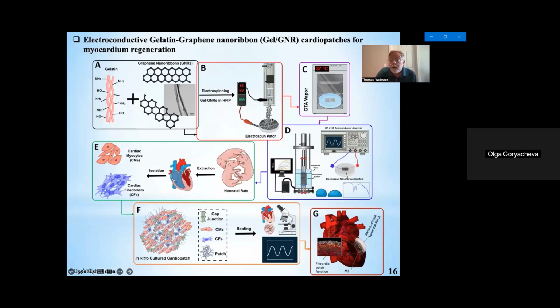You can electrospin these materials into an appropriate patch orientation. This is also during electrospinning when you can align the graphene nanofibers or nanoribbons to basically make that anisotropic electrical, anisotropic mechanical properties. So during electrospinning, you can actually make a larger device that has these attractive anisotropic properties. We, of course, have characterized these, and I'll show you results for electrical properties and mechanical properties to ensure that they meet standards. We have completed results on in vitro and some animal studies showing that they can regenerate healthy tissue in the area of damaged tissue.